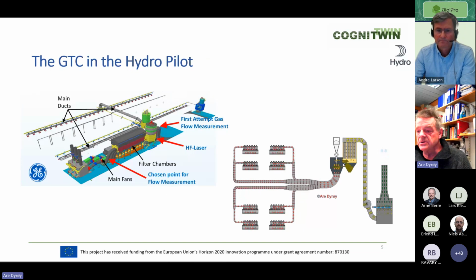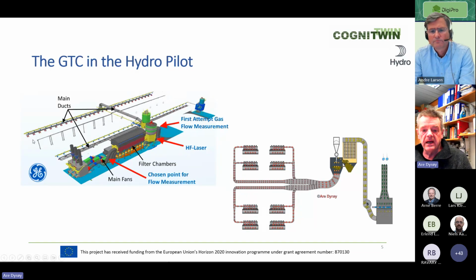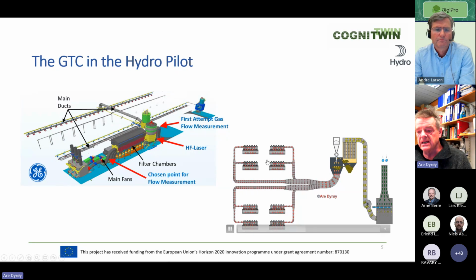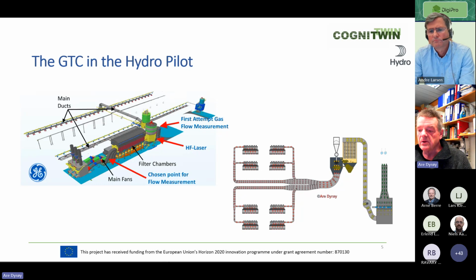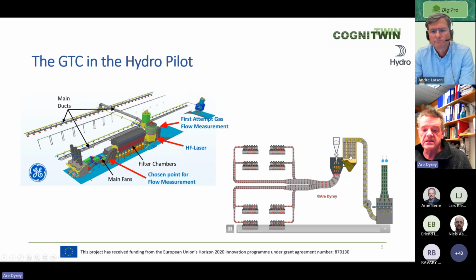This is the system in question. This is the Karmøy technology pilot, where we have the gas ducts coming from the pots going to the GTC, and the gas is collected from the cells, gone through a reactor where it meets the smelter grade alumina, both primary and also recirculated alumina, to absorb the HF. And mostly these GTCs are working with an efficiency of 99.9 something in terms of recovering the fluoride.